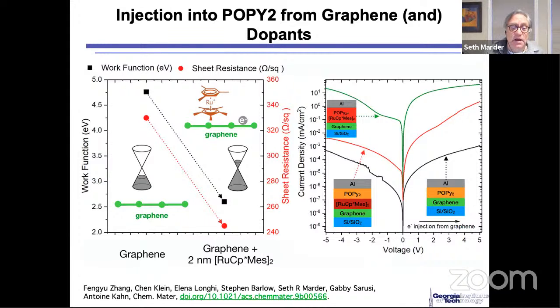My worry was, once there is a diffusion, then you see the optical effects if you're making, for example, LEDs, or if you're making transistors. You wouldn't see optical effects, and the reason is that the doping level is at the level of a nanometer or less. We're not at the level of depositing an electron transport layer here. We are doing very, very low doping.